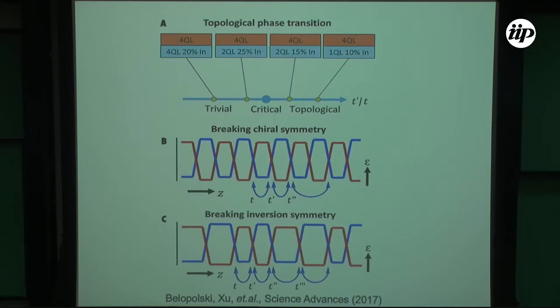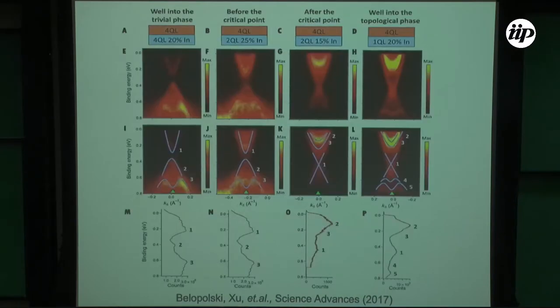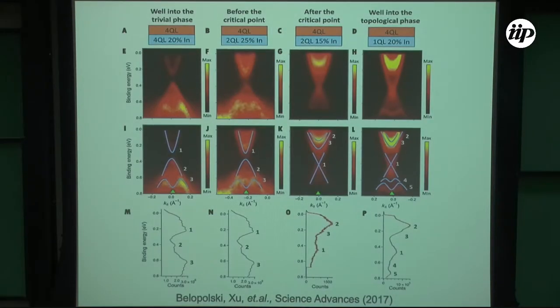For now, for simplicity, let me not introduce further parameters, which would make it more rich, but first discuss the experiment, what we see. My top layer is 4 nanometer, 4QL. In all these cases, all I'm varying is the second layer, or the insulating layer. It's now 4 nanometer, here it's 2 nanometer, but 25% indium, 2 nanometer, but 15% indium, 1 nanometer, now 20% indium. Indium makes it more insulating, and